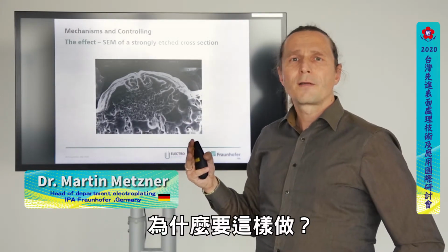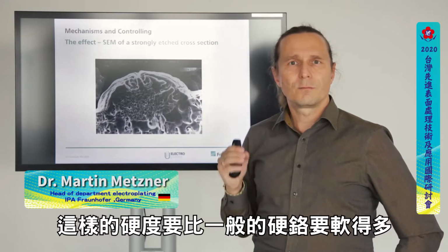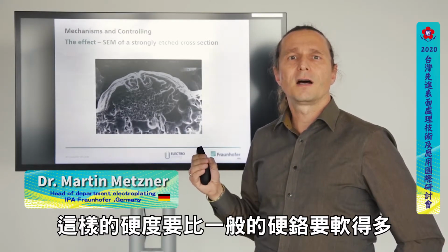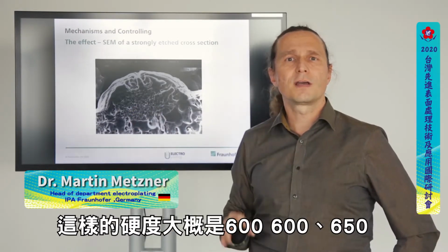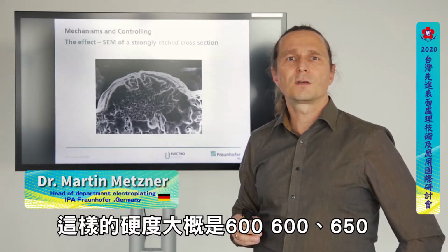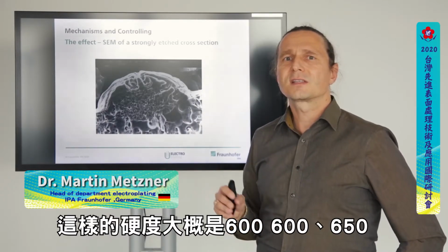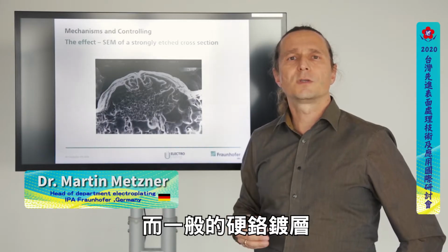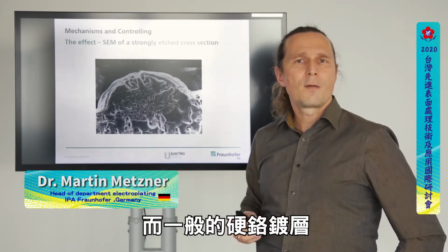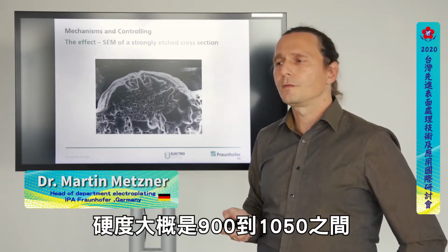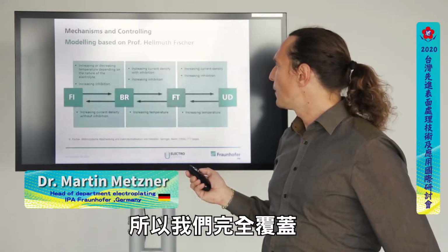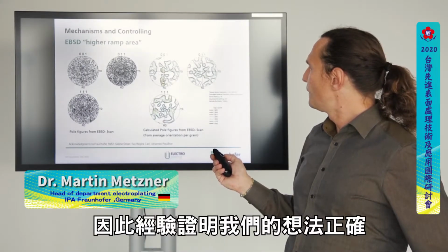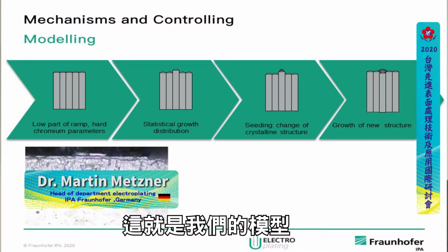Why do we do this? Quite simple. This one is much more soft than the normal hard chromium. So in here we talk about a hardness of 600 Vickers or something like that, 600, 650, whereas in normal hard chromium plating we've got something between 900 and 1050 Vickers. So we just cover the whole thing. Experiments have proved that we were right. So this is the model we have in there.